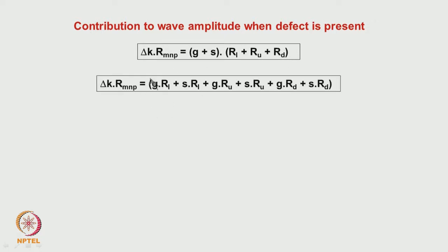Now if we just expand this expression, G dot RL is the term which is essentially going to be an integer, correct? G is a perfect translation vector, RL corresponds to different lattice points, each point representing a unit cell. S is a deviation from the Bragg condition.